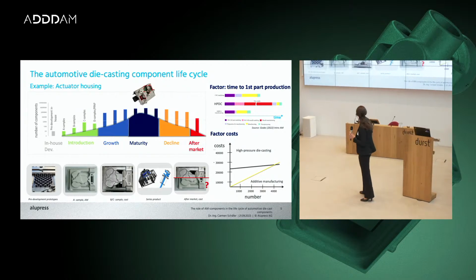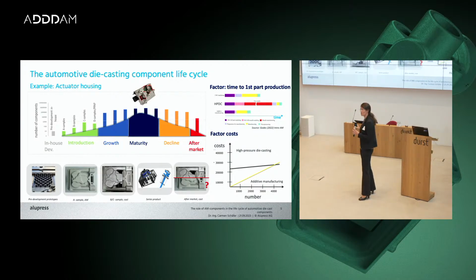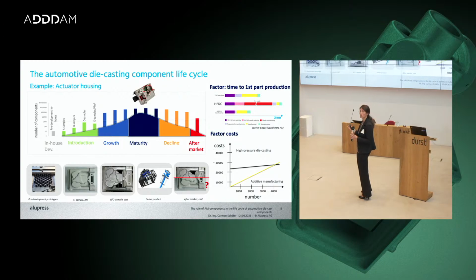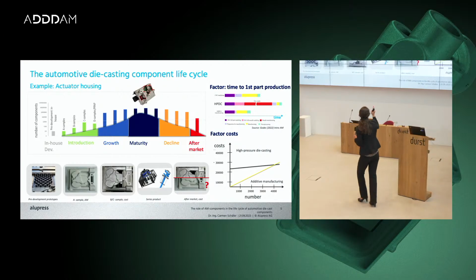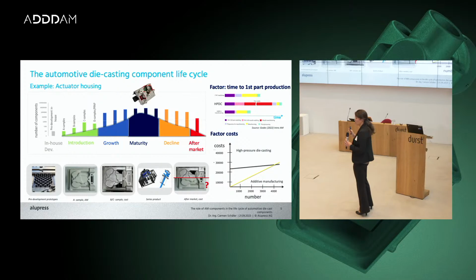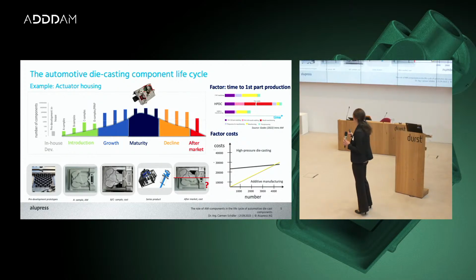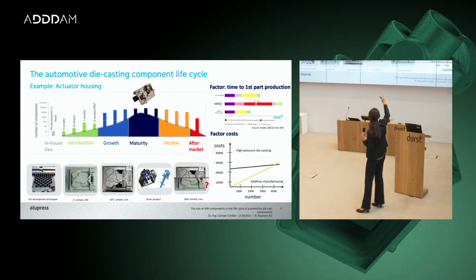And that is another possibility. You see the die casting and additive manufactured components with higher numbers, usually 500 to 5,000 pieces per year. There are two factors that are important. First is the time to the first prototype. And you see there is high pressure die casting. This reddish area is these 12 weeks, a long time.